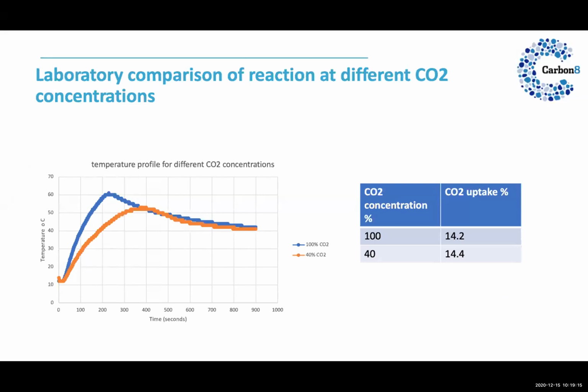So it's very difficult to play with the CO2 in the container, because obviously you're starting off with a 10% concentration of gas. But I want to emphasize that there are some advantages of capturing the flue gas directly. One of the problems with carbonation, as we do it in carbonate systems, which is very much at atmospheric temperatures and pressures, the solubility of CO2 is related to the temperature, and the principle of the process is that the CO2 will ionize in a thin film of water.